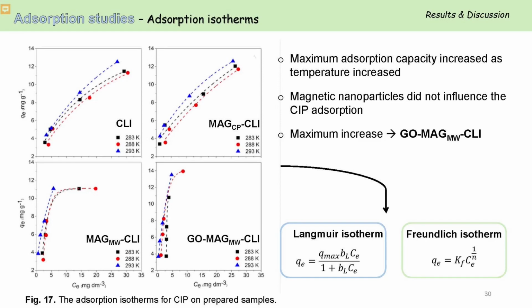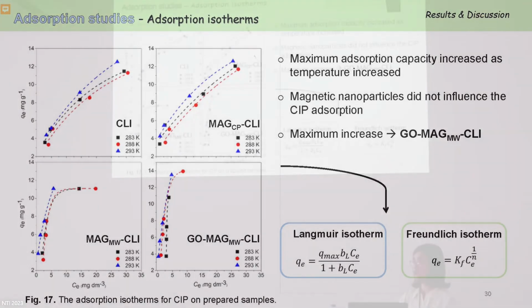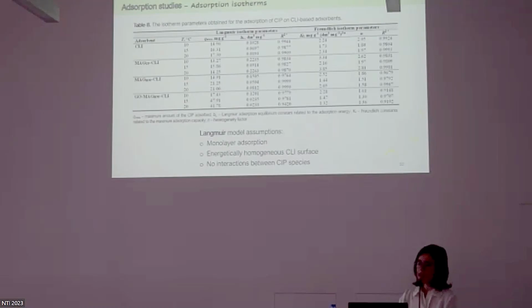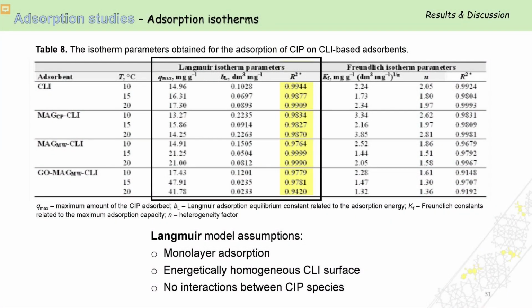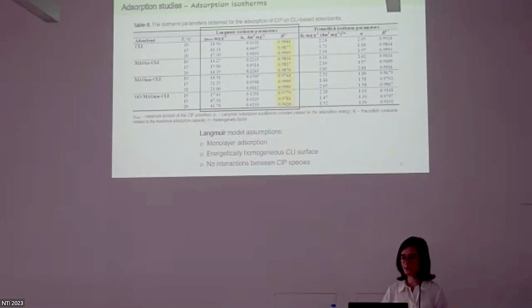The results of the isotherm study were then analyzed by the Langmuir and Freundlich isotherms. According to the results, the Langmuir isotherm slightly better describes the adsorption of ciprofloxacin onto the synthesized adsorbents. This indicates that the adsorption proceeds as a monolayer, that all the sites on the clinoptilolite are energetically homogeneous, and that there's no interaction between adjacent species of ciprofloxacin on the adsorbent surface.